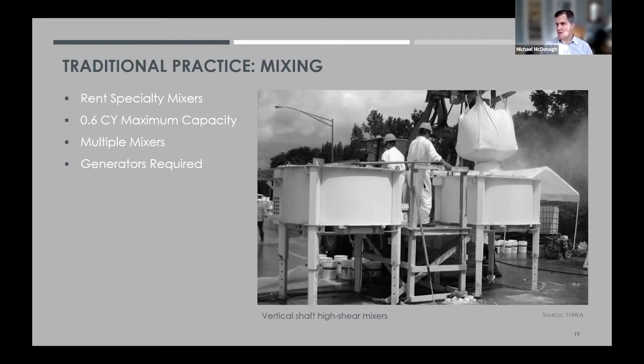Very commonly, you'll see mixers such as the type in the photo here, vertical shaft high shear mixers. They come in different sizes, but the largest can only mix 0.6 cubic yards. They sometimes break down, and given their small capacity, typically multiple mixers are required, at least a minimum of 2. The contractor must also rent relatively large generators to power these mixers. In this photo, you can see dry UHPC mix being loaded into a mixer.